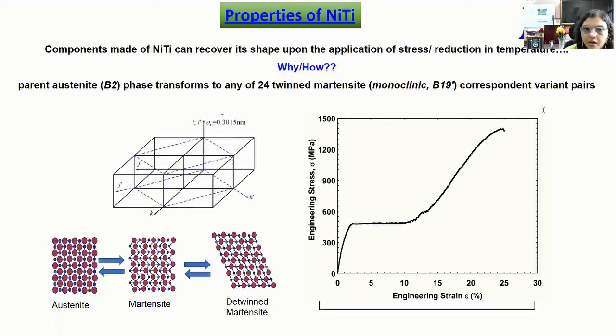So unless there are any precipitates or any compositional changes happening, this is not directly affecting the ability of the material to recover its shape. But again, a refined structure in a polycrystalline material means the chances for different grains to behave differently are higher. Which of the CVPs will activate and which will give more pseudoelasticity compared to others, as I have shown in the effect of grain orientation, such things cannot be ignored. In that sense, the DRX structure may have some effect. It will be a nice area to explore further, I guess.